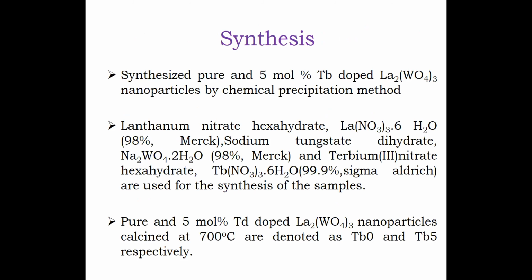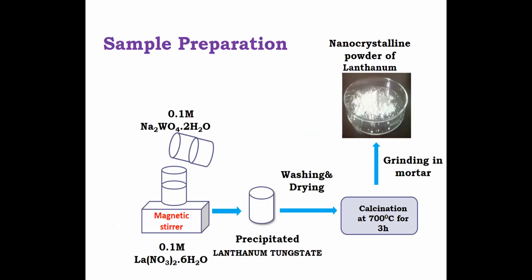About the synthesis, we synthesized pure and 5 mole percentage terbium doped lanthanum tungstate nanoparticles by chemical precipitation method. For this, analytical grade chemicals such as lanthanum nitrate hexahydrate, sodium tungstate dihydrate, and terbium nitrate hexahydrate are used. In this presentation, the pristine sample is termed as TB0 and the doped sample is termed as TB5. Then move on to the sample preparation. This is the schematic representation of the synthesis procedure.